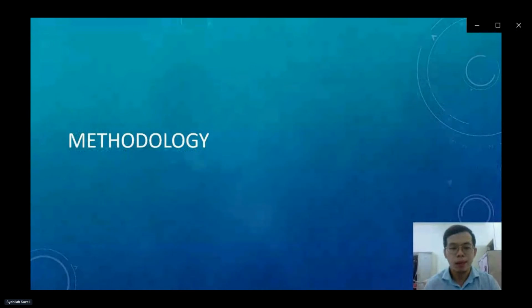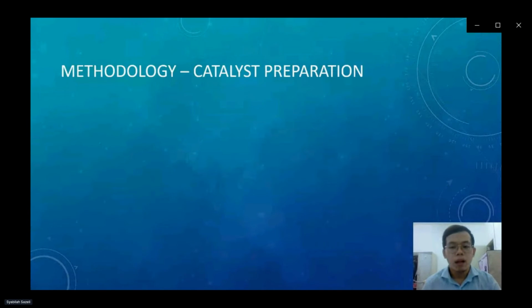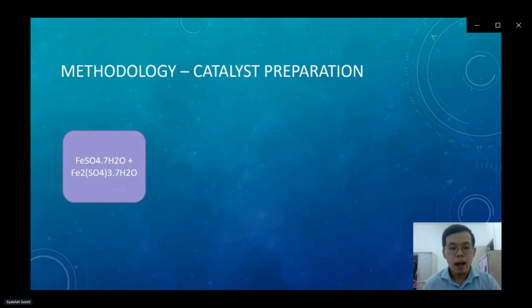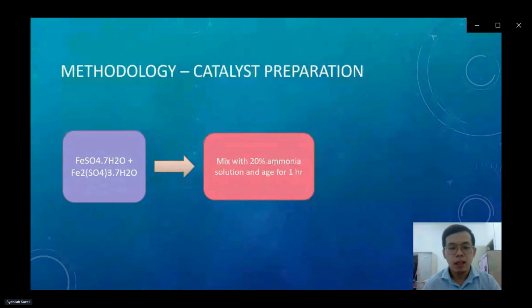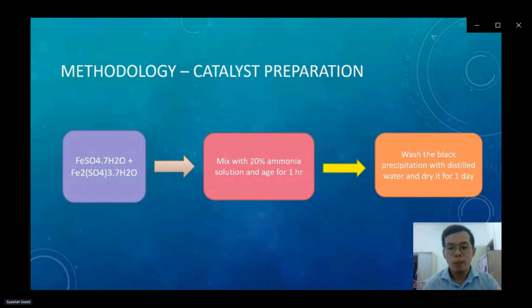Now, I would like to explain the methodology used for the project. First is the catalyst preparation. In order to produce the CLW/Fe3O4, we need to produce the Fe3O4 first. The iron(II) sulfate hydrate is mixed with the iron(III) sulfate hydrate, then the product of these two is mixed with 20% ammonia solution and stirred for 1 hour. After that, we wash the black precipitate with distilled water and dry it for 1 day. This is the process to produce the Fe3O4.